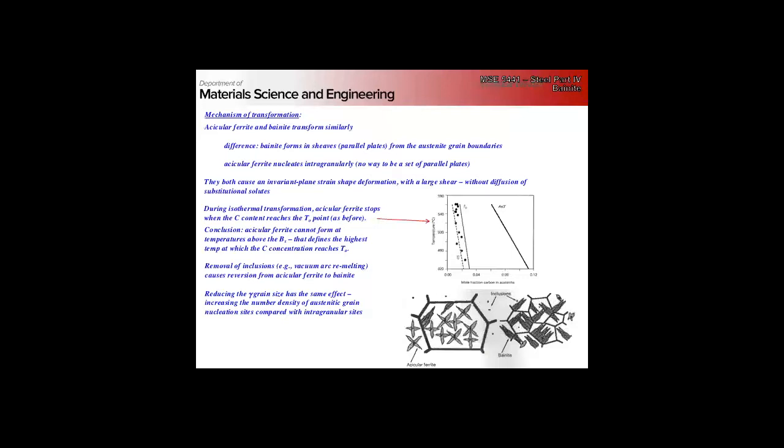If we have small grains, right, a lot more surface area, right? Remember, surface area goes by what with respect to the radius? Right, squares, right? And so making the grains a little bit smaller gives you a drastic increase in surface area, a lot more nucleation sites. So if we make our austenite grains smaller, we eliminate acicular ferrite.